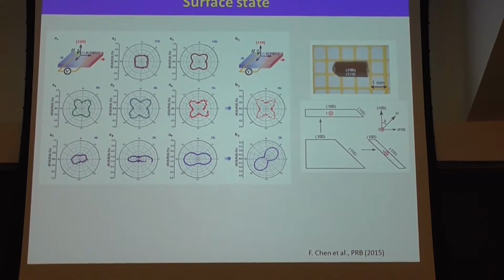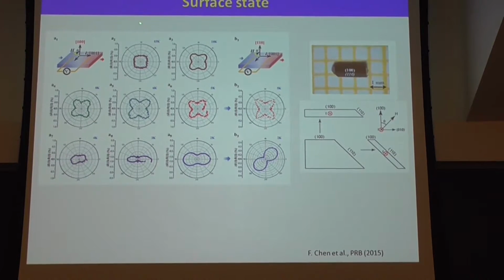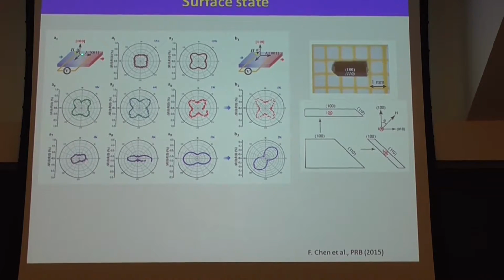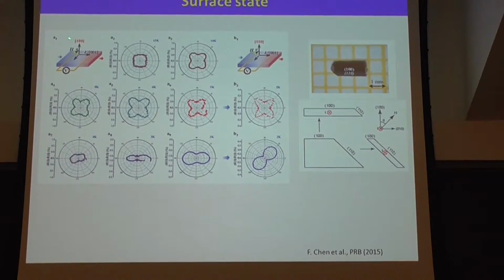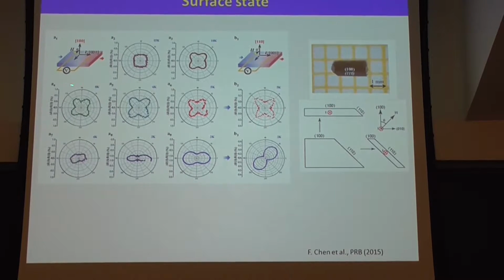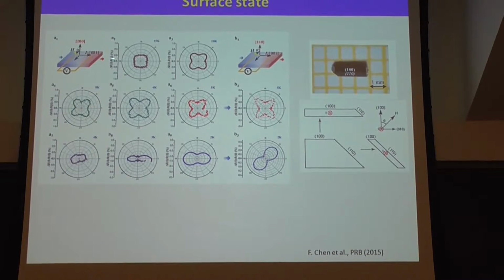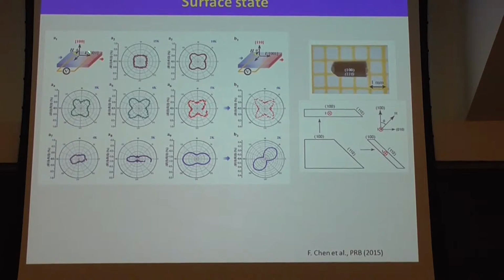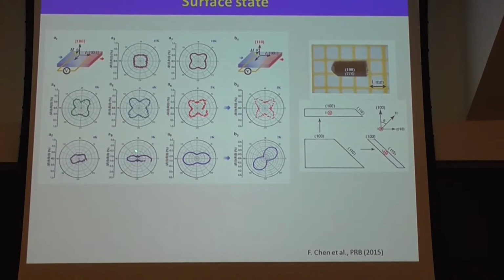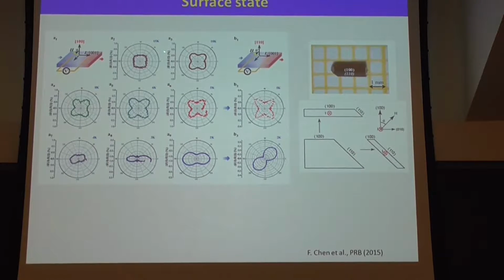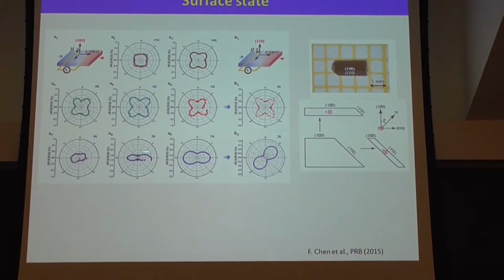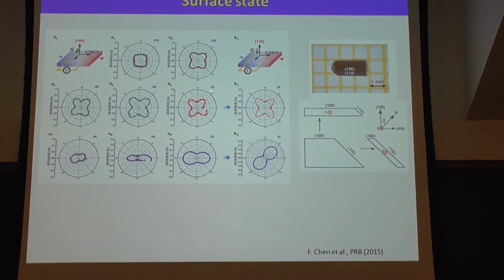Also, we do some anisotropic magnetic resistance. For this single crystal, magnetic resistance, we just use this surface, 100. Then the current is kept along this 001. Then we rotate the field in this plane. You can see from the high temperature, 50 Kelvin, to 10 Kelvin, to 5 Kelvin,